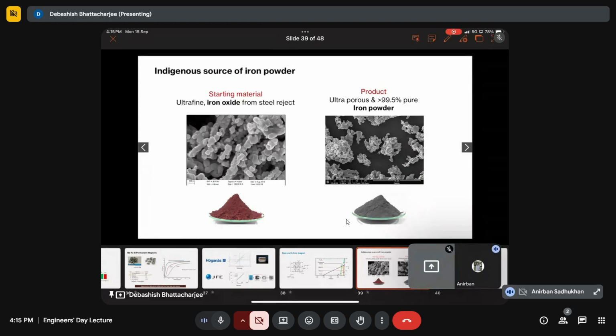But when you do cold rolling, you have to ensure that the rust doesn't get rolled in. So you have to do pickling and take away the rust. That rust is very superficial and it's very fine. So when you filter the acid that has gone into the pickling process, you get a residue which is almost pure Fe2O3.